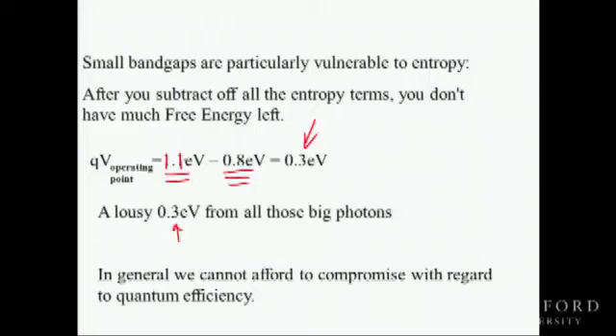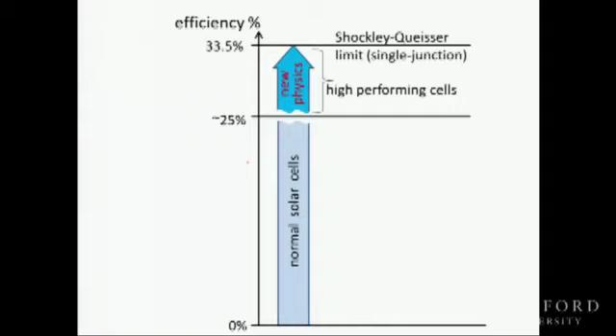Okay. And so this is a very strong statement that if you have an incredibly clever idea, and just to mention hot carriers to produce more electron-hole pairs, you have to have a small band gap. If you have a small band gap, you run into this problem with entropy. Those infrared photons, those small band gaps, don't have enough free energy to be worth the struggle. And unfortunately, the decision makers are not always aware of the thermodynamics, even the scientists. Okay, so the title had high efficiency. So let me get into the high efficiency now.